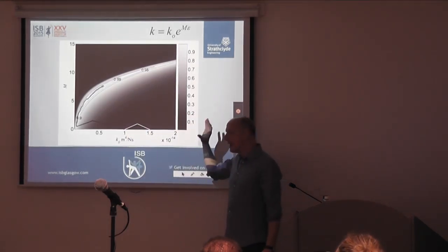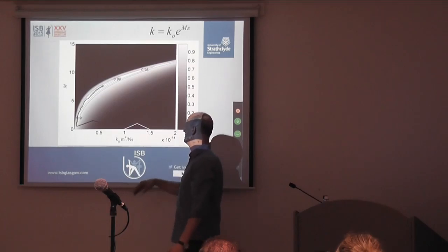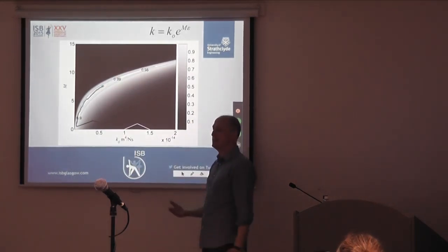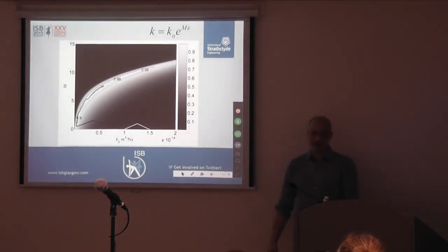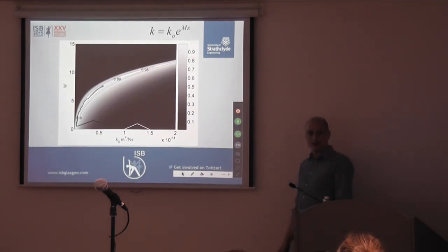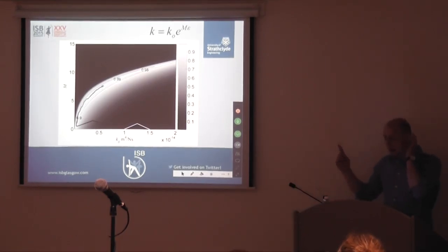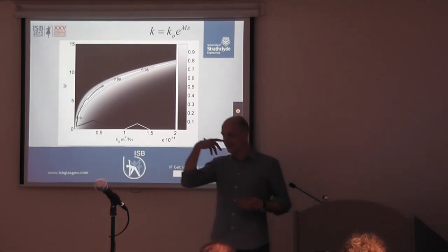This is showing here that there's a wide variety of initial permeability and M which gives a pretty good fit. So I think these models are quite insensitive to permeability. We're getting a factor of probably 10 between 0.1 and 1 here. That's a huge change in initial permeability, by a factor of 10, and you can still get a really good fit by changing another parameter in the model. I think that's a problem. Okay, multi-parameter systems, generally there's a variety of combinations of parameters that get the same mechanics. And these aren't that complicated models, let alone if you throw in fiber direction or hyperelasticity or other parameters in there.